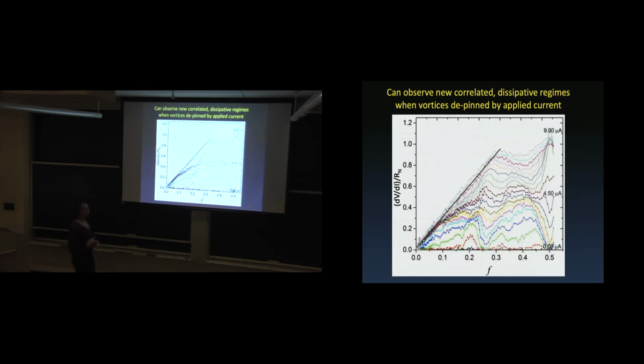Okay, so this is the exact same data, except here, instead of having temperature, I'm driving it with a current. So if you remember before, this is frustration. It's only going up to half filling right now, but you can see basically, for low currents, it's superconducting, and then at a quarter filling, I get a little dip, and at a half filling, it's superconducting. So same thing here, right? I get a dip at a quarter filling, and I get a dip at half filling. It's very similar, except there's a lot more going on here.